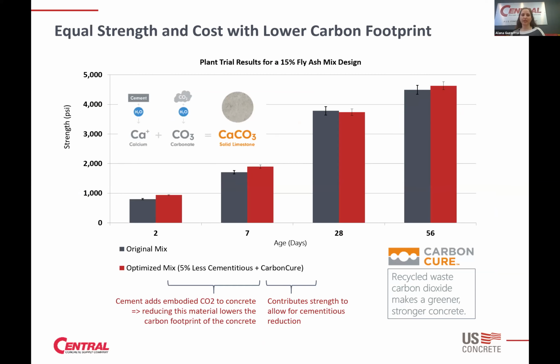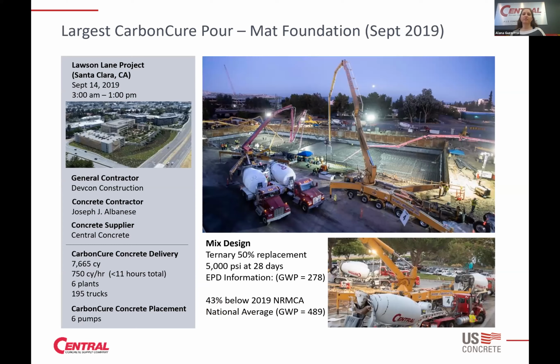This is something that we've done successfully in both of our markets. Particularly, we have it available at 7 different plants in the San Francisco market. In 2019, we were actually able to do a mat slab delivering out of 6 different plants for over 7,600 yards in just under 11 hours. So we were producing that at a rate of 750 cubic yards an hour. The amount of sequestered CO2 is about 0.5 pound to 1 pound per cubic yard. And with this, we're able to look for opportunities as well to optimize the mix and further reduce the amount of cementitious material.